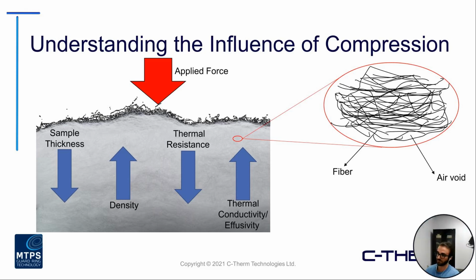and finally that results in an increase to your thermal conductivity or thermal effusivity measurements. And the reason for this, essentially, if you take a close-up look at, in this example, this filled fiber type sample, you're going to have these individual strands or loops of fibers interdispersed with these different air voids. And if it's uncompressed, there's obviously going to be much more air present.